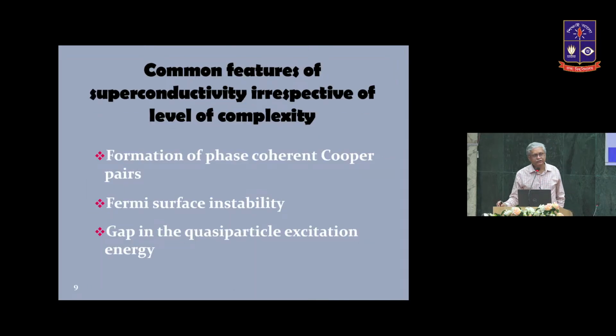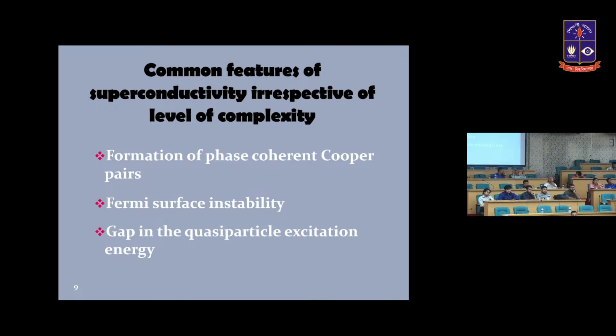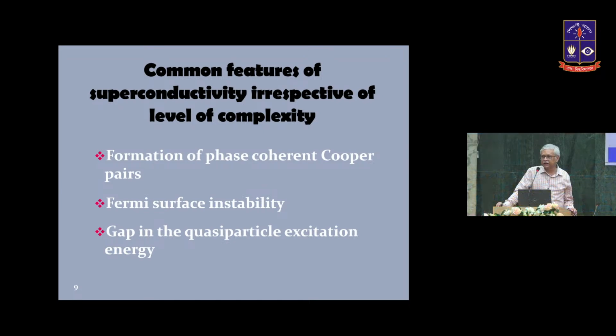Okay, but still they are superconductors, so there must be common features, and the common features are these. You need phase-coherent Cooper pairs for superconductivity, and that will lead to a Fermi surface instability. And this instability will open a gap centered around the Fermi level in the quasi-particle excitation energy. And all these three factors are seen in copper oxide superconductors, like the ordinary BCS, Bardeen-Cooper-Schrieffer superconductors.